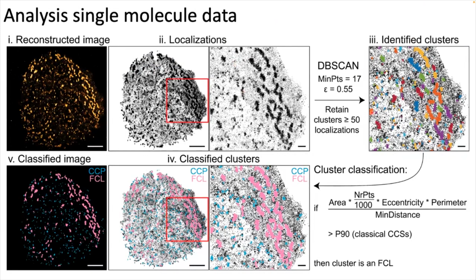And we do an additional step, that is to say, okay, we only keep the clusters that have more than 50. So for it to be classified as a cluster, it has to have a minimum of 17. And if we increase this value here, it starts merging clusters together. So we kept it at 17, but then for us to take it into consideration in our analysis, it needs to have at least 50. So it was a very empirical way of finding these parameters.